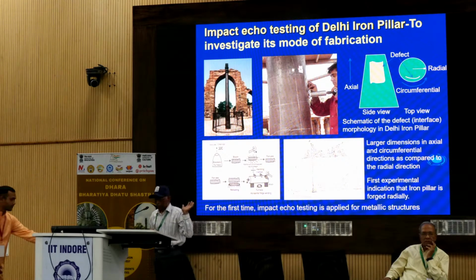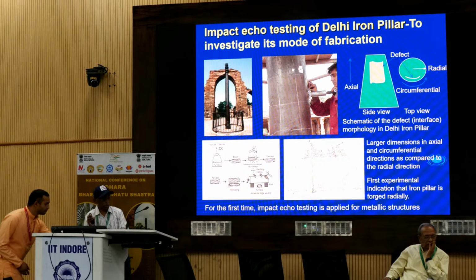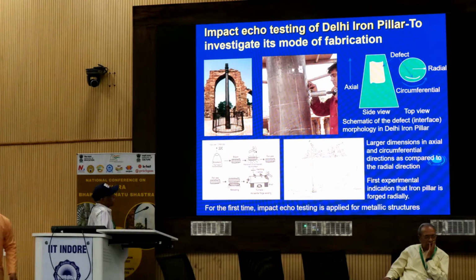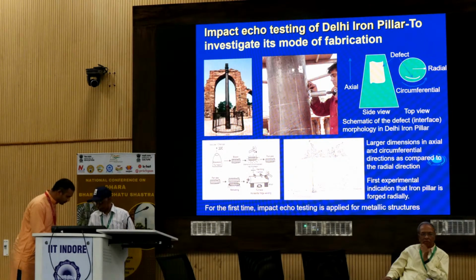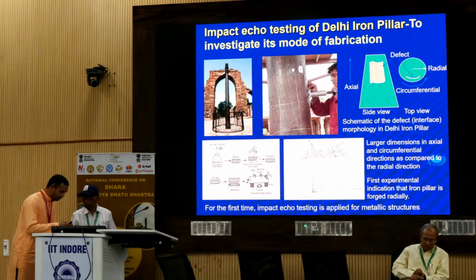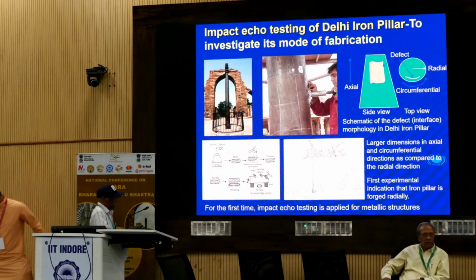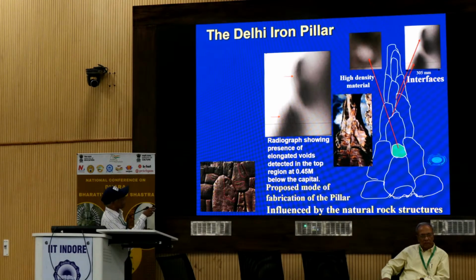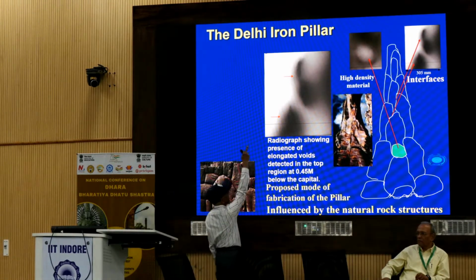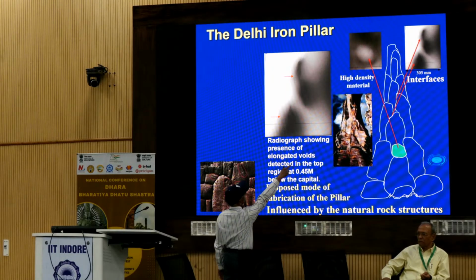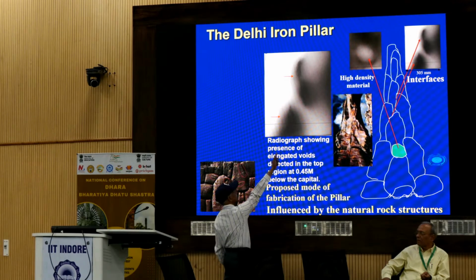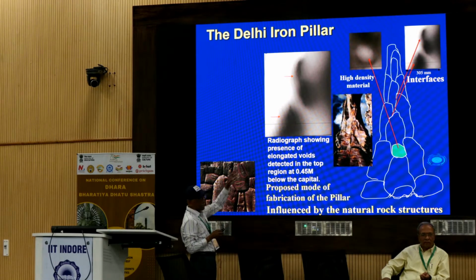So what is done is that when you do the radiography, okay, I'll use the hand, no problem. It got stuck. Okay, great. So when you do that, you can see that the orientations of the interface, this is in the axial direction of the pillar. You see that these are all axial and then circumferentially oriented. So if the interface is not like that, you won't see the contrast from the radiography.